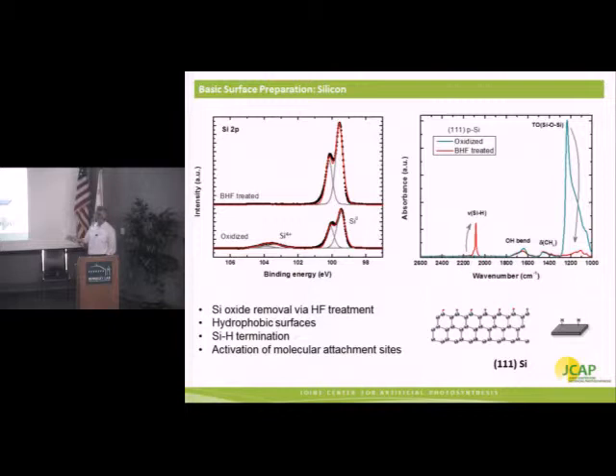So in this case, we have silicon. It has a native oxide when you receive it from the manufacturer. We can treat it with HF, completely remove that oxide, and from infrared spectroscopy, we do see that we have silicon-hydrogen (Si-H) modes directly on the surface. These are the sites that allow us to do chemistry on the surface of silicon.